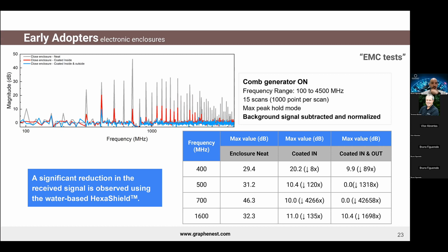And again, please bear in mind that these spectra were normalized, and we have to subtract the background signal for the sake of easiness, and to take into consideration all the noise coming from other networks. But despite that, what we could immediately observe was a significant reduction in the received signal using our water-based HexaShield. And this becomes more prominent in the box that was coated inside and outside, so the blue spectrum. So as you can see, the peaks are much smaller.